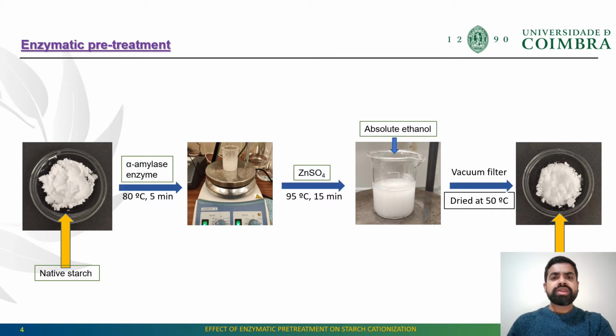After cooking, the starch solution was cooled down and absolute ethanol was added to precipitate the cooked starch, which was vacuum filtered, dried and stored in the oven at 50 degrees centigrade. In the enzymatic cooking, the alpha amylase enzyme cleaves the 1,4-alpha-D-glucopyranosyl linkage of amylose and amylopectin, which reduces the degree of polymerization of starch polymer.